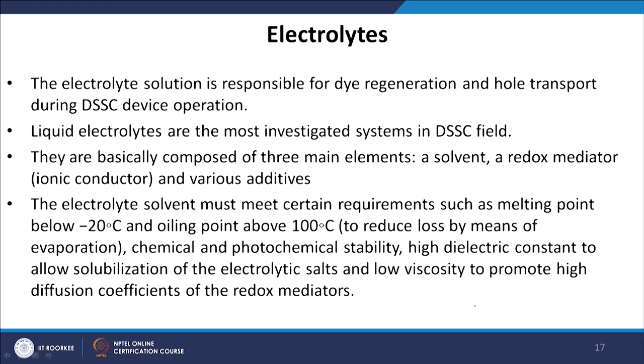The electrolyte solvent must meet certain requirements: a melting point below −20°C and a boiling point above 100°C to reduce losses by evaporation. Chemical and photochemical stability are also required. The solvent should have a high dielectric constant to allow solubilization of the electrolyte salts, and low viscosity to promote a high diffusion coefficient of the redox mediator.